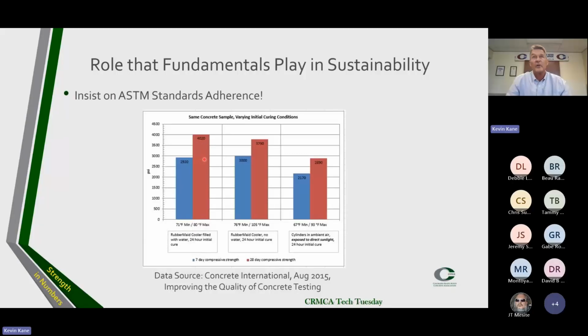Another set of cylinders from that same sample of concrete, we put in a Rubbermaid cooler with no water for a 24-hour initial cure. And look what the temperature went up to. The heat of hydration from the concrete cylinders was detrimental to maintaining that 80-degree maximum temperature. It went up to 105 degrees, and there was a resulting decline in the later age strength development. We all know this, and yet we still have the problem.